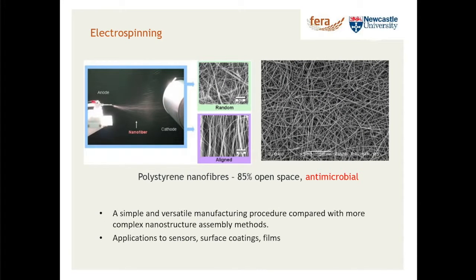So this is now sort of heading into the slightly technical part now. I've been involved in the use of biopolymers and investigating their uses as alternative packaging materials or alternative packaging solutions. And one approach is electrospinning. This technology has been around for quite some time now. Sort of mid-1930s it was first described. But essentially what we have is a needle or a nozzle which is at a high voltage difference from a collecting plate, and using something like a syringe or some sort of controlled slow pump, you eject out the liquid which forms fibers as it comes out. And this is what we see typically, usually a random arrangement of nano-sized fibers.